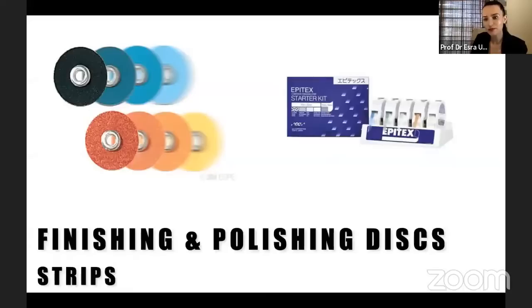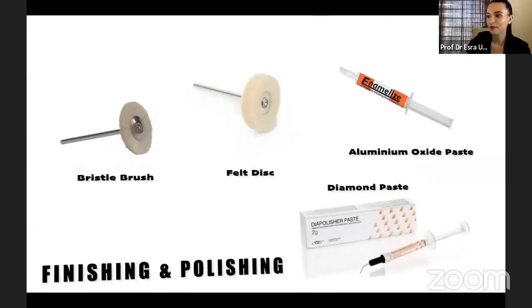We use polishing strips. In the past, they were a little bit thick, so we used them under the contact point. But today, there are also good, very thin products like Epitex. Epitex strips are ultra thin because the abrasive particles are not bonded to the strip by an adhesive in that product. Thanks to this feature, Epitex allows easier access in tight contact points, helping to minimize gingival damage, and you can also use them very slowly between the contact points, in the contact points. This is an advantage, not just under the contact points.